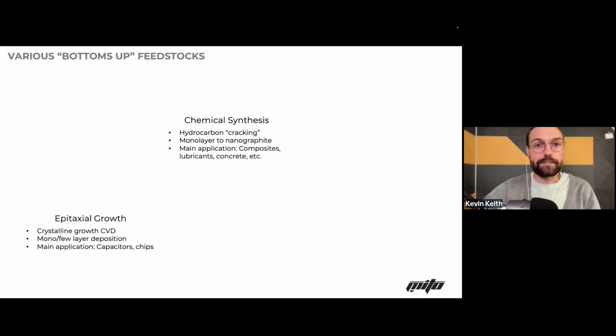Then you have epitaxial growth, where it's a crystalline growth CVD. Picture, if anybody has kids, making rock candy is a very simple way to see this, where you have a very highly concentrated sugar water. And as that water dries out, crystals grow, and then that rock candy forms around that single crystal. Same thing with epitaxial growth, in that you have a certain solution that, as a crystal forms on a substrate, the rest of the carbon crystals grow around it. You can have mono to few layer deposition from this. Main applications from this are capacitors and chips, very highly dependent on thermal and electrical throughput, that you can have smaller scale production methods because of that crystalline growth.